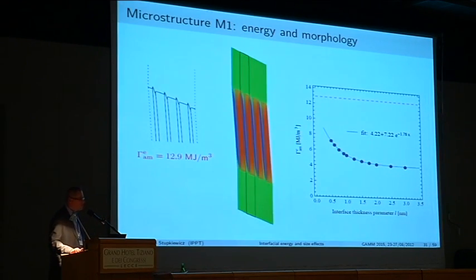However, if we look at microstructure M1, again, the morphology is similar. We don't see this cusp here, but otherwise it's really similar. But in terms of the energies, there is a big difference here. So if we adopt this fit, actually this fit would go up to 12 more or less, or 11 and a half, sorry.